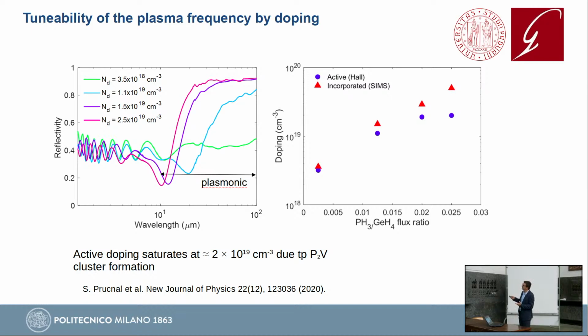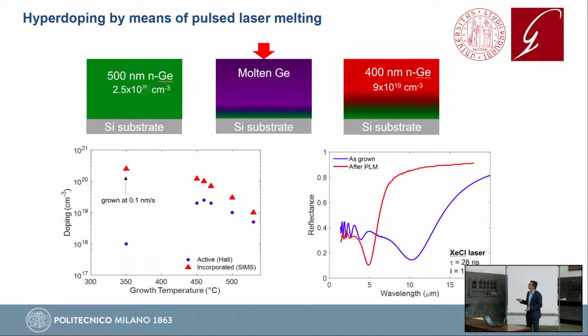So again, we need something to improve our material. Actually, this limit is a fundamental limit of this system, given by the formation of clusters between phosphorus and vacancies. And so again, we need something to shock our system and go outside what equilibrium will tell us, which is you cannot go above a few 10^19 during epitaxial growth.